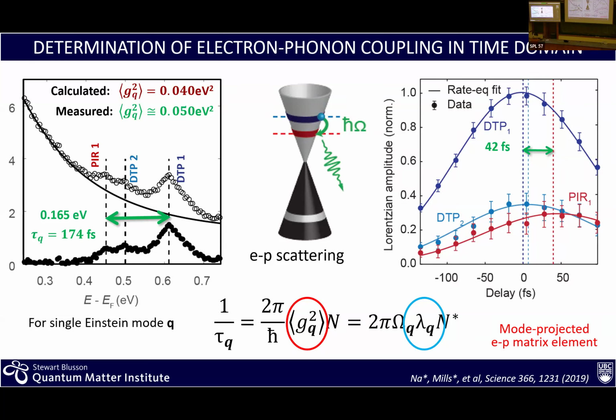And not only that, in fact you have two optically allowed transitions. In the system we have three optically allowed transitions, but one we missed is above here and we didn't measure it. All of them will see intensity coming down through electron-electron scattering, which gives you the tail, and electron-phonon scattering. So you get all these peaks. In the actual rate equation that we use to analyze the data, we include all these peaks. So it's a combination of quite a few features superimposing with each other and then limiting resolution.